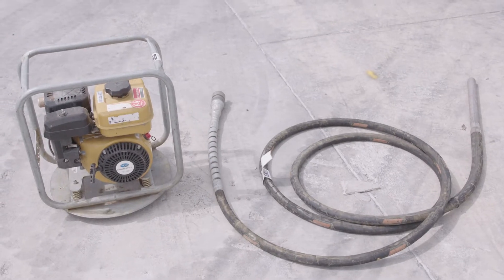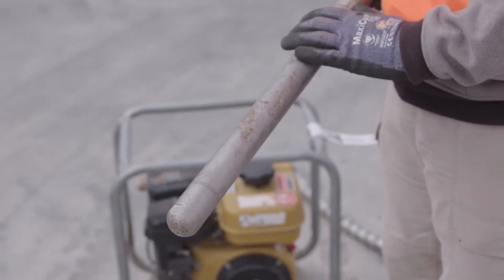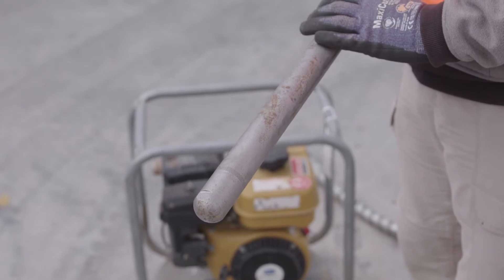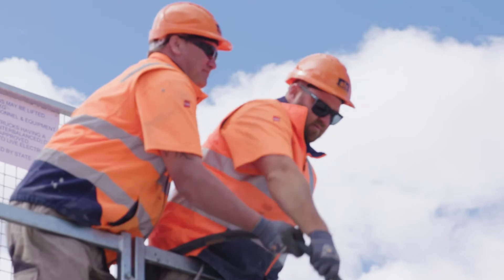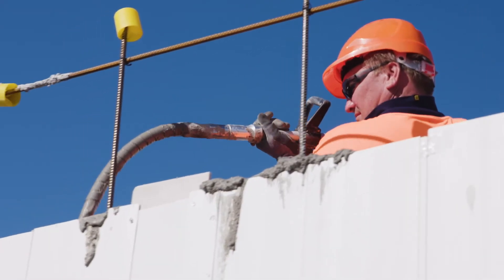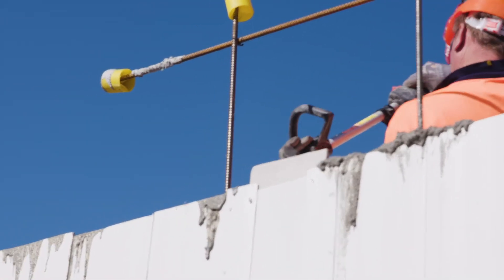For the vibration of concrete, a concrete vibrator with flexible shaft and 38mm head is to be used. Place the vibrator at the bottom level of the pour, maximum 1500mm height, and then move up and out of the pour zone slowly over a period of 5-10 seconds.